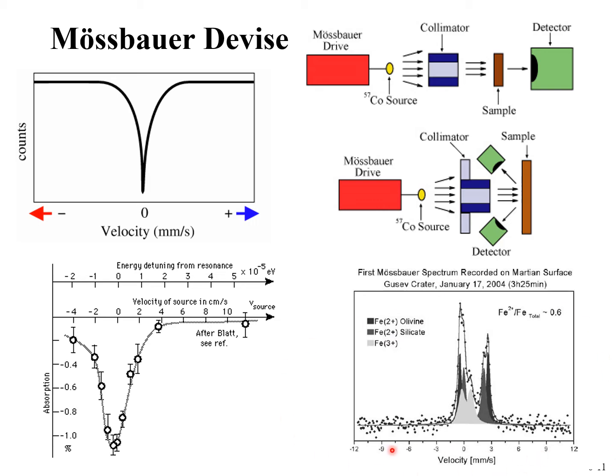Here's the velocity of the source, the absorption lines. And what one can do is look at these chemical shifts to get an idea of what iron components are present. And this was important for looking at the total amount of iron 2 relative to total iron. And this gave an idea of oxidation on the Martian surface, which would give an idea about the presence of water.